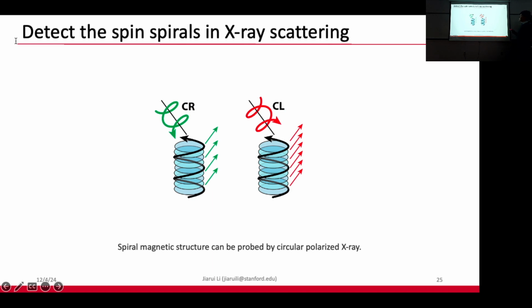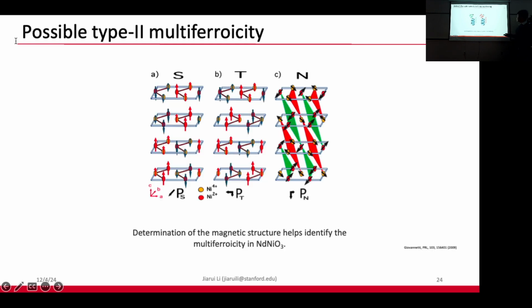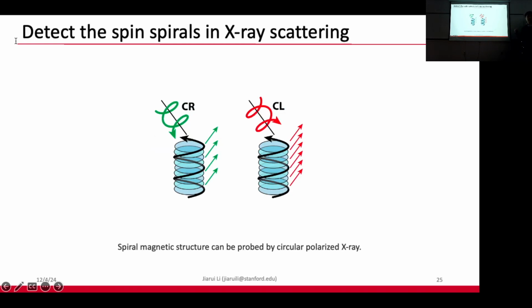Why is this magnetic structure so hard to determine? The reason is that in order to determine this vectorial magnetic structure, because it's a vectorial field, all of the measurements that we make are actually projecting this vectorial field along some directions or into some plane. And after these projections, any of these non-collinear or collinear magnetic structures become equivalent. Therefore, a lot of measurements cannot distinguish between these 2.